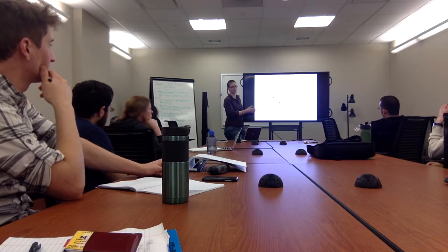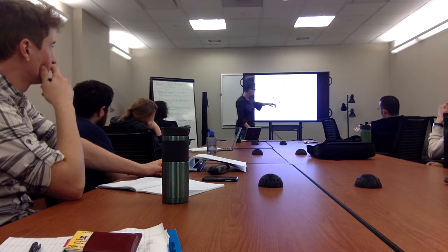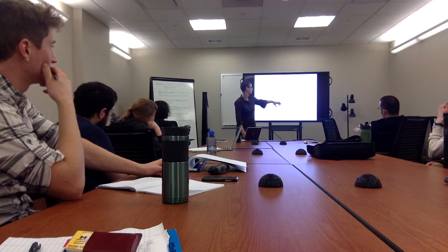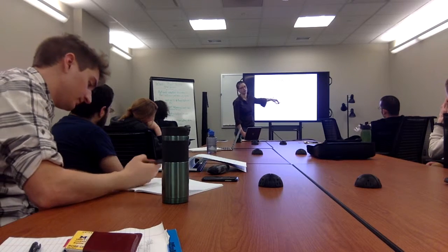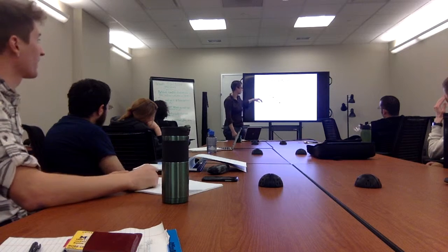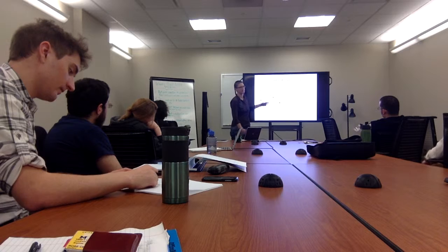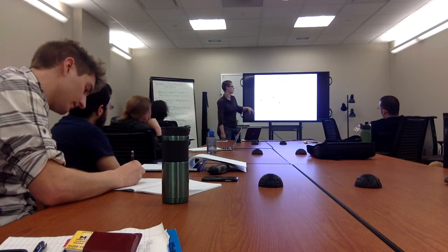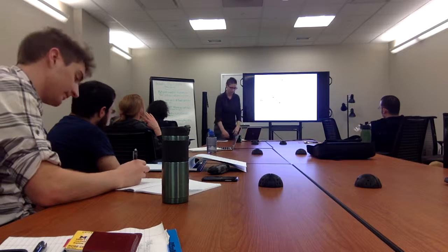That can easily, martensitically or something, transform into the structure you want. If that phase can form first and then has an easy time transitioning over to the phase you want in the end, then that can help you. But the same type of process can hurt you too, if the system tends to form clusters that are not consistent with what you eventually want to form, because then you have an even larger step to get over.